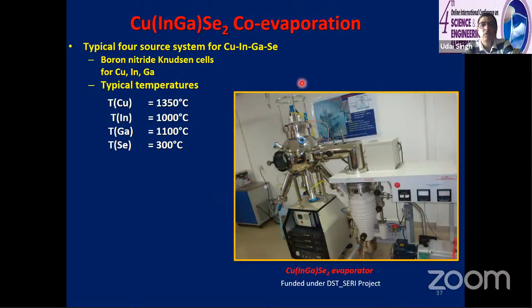So this is the system we use. This is funded by the DST. So you can see these are the four sources: copper, indium, gallium, and selenium. So you can use all simultaneously. We are controlling the flux by the temperature only. For different materials, you use different temperatures to control the flux. We don't have in situ measurement for the flux and the thickness. So it's basically hit and trial, like you first try to optimize copper for different temperature and time, to see how much thickness you are getting.